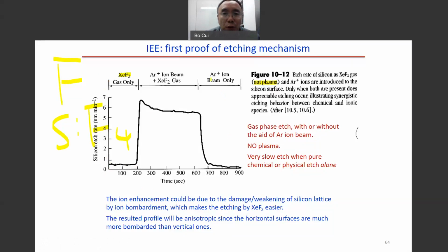The same is true for argon ion bombardment. We have the argon ion bombardment, and the etch rate is also slow. But when we have the argon ion bombardment plus the xenon difluoride gas, you see the etch rate is much faster. This is because the argon ion will damage the silicon lattice. When the silicon lattice gets damaged, the etch rate will be much higher.